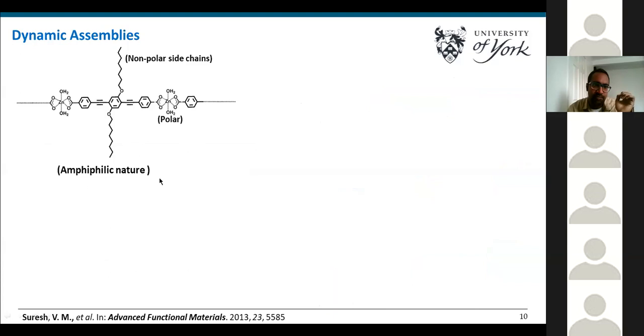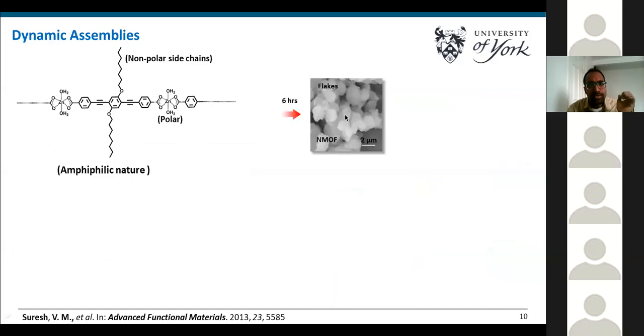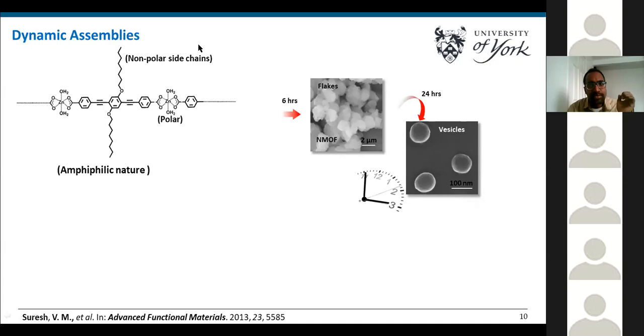We would like to see such a transformation by changing the reaction time. As we have seen before, at 6 hours, we see nanoflake-like structures. Now, on increasing the reaction time to 24 hours, we see a conversion of nanoflakes to vesicular nanostructures. These vesicular nanostructures are also evident from TEM analysis, and the thickness of the wall is 4 to 5 layers of 2D coordination sheets.